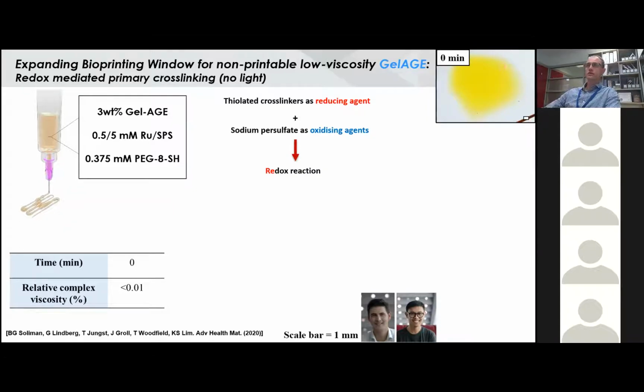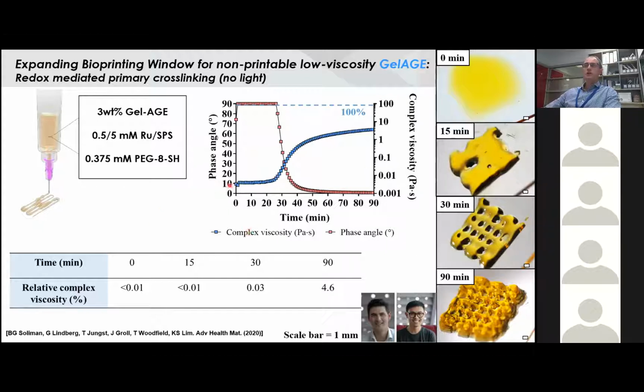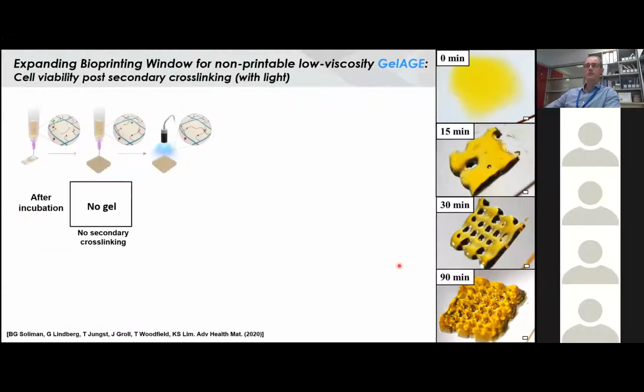So essentially it's non-printable. But if we think about some of our chemistry, the thiolated cross-linkers that we use act as a reducing agent, and the sodium persulfate in the photoinitiator acts as an oxidizing agent, so essentially we do have a redox reaction occurring. If you leave that running over time, is there some way that we can change the properties of our bioinks over time? What this shows is that we can get a nice sol-gel transition over time, and that we actually increase the complex viscosity of these materials due to this redox. Again, this is without any light. We're purely relying on redox cross-linking mechanisms running.